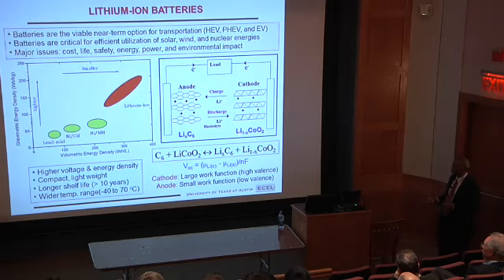With lithium cobalt oxide, you can store 1 lithium per cobalt, but in the practical battery, you can use only half of that. If you use more than that, you will have Boeing fire, you have Dell recall, that kind of problem. So we are not even able to use the full capacity of this material because of the problems. So that's for the energy density.